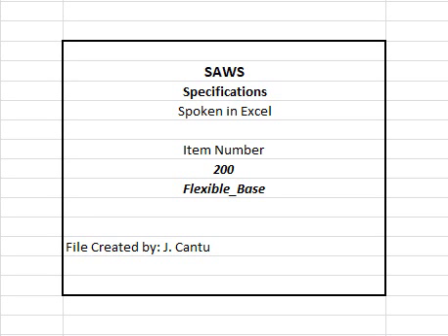7. Flexible base shall be compacted to a relative dry density of not less than 95% of the maximum dry density as determined in accordance with TXDOT test method Tex 113E. 8. All density tests will be made within 24 hours after compaction operations are completed. 9.